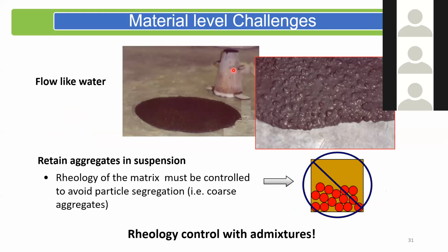So this is the genesis of SCC. We want concrete to flow like water. So when I lift the slump cone, it should self-level. It should flow under gravity. It should find its own level, and it should be able to flow by carrying the aggregate with it. And this is where the challenge lies, because if I have concrete that flows more, that means I have to reduce the viscosity. I have to make it less viscous, otherwise it won't flow.